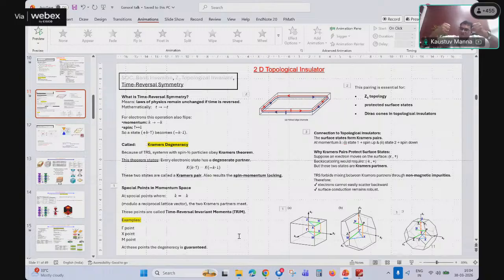So it is possible that even beyond uniaxial compression, even high pressure works the same way. You take a material, apply very high gigapascal pressure, and you can change the crystal symmetry a little bit. If symmetry is gone, then the topological protection will also be changed, right? If earlier, let's say, there was a cubic Brillouin zone, and there was one band crossing at the point R, and now by symmetry manipulation you have gone to a symmetry where at the R point there is no crystal symmetry, then if there was a band crossing at R, there is nothing to protect it, it will simply gap out. So from a topological state to a non-topological state you will go. So this is how the symmetry controls the topological states.